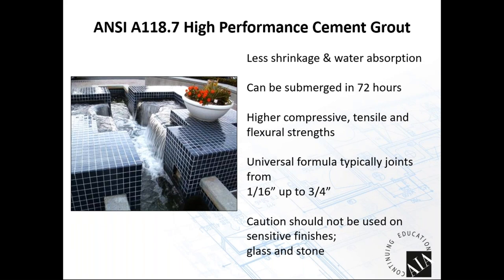But we're using a fine aggregate in these grouts, and instead of needing an unsanded grout for a tight joint, as you would with the traditional ANSI A118.6 grout, we can use one grout that'll go anywhere from 1/16 of an inch all the way up to 3/4 of an inch in a joint and not have cracking, shrinking, or problems that a typical Portland cement